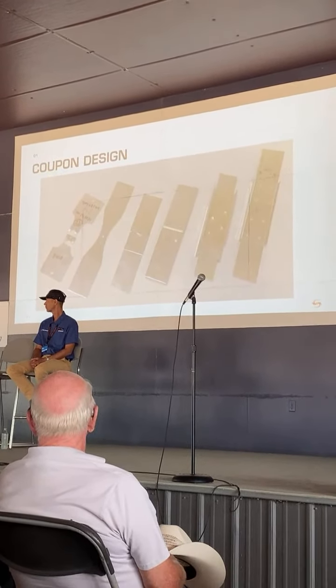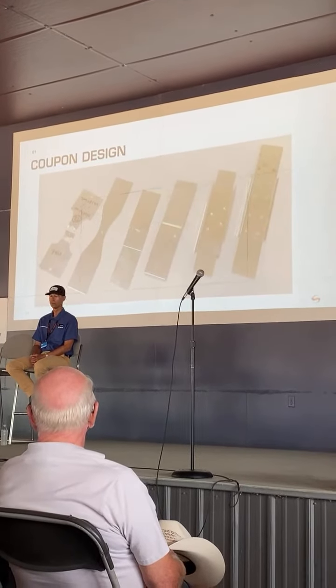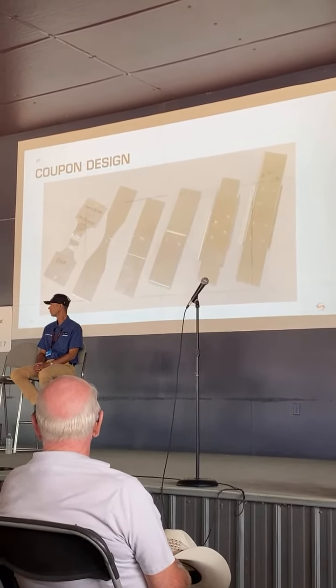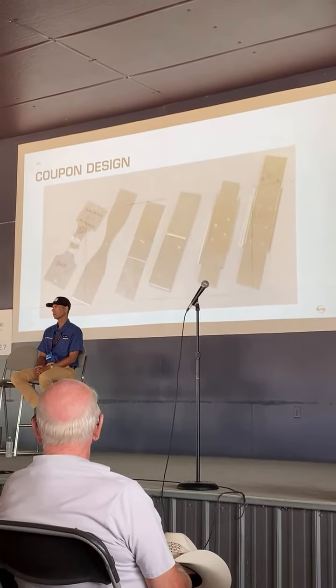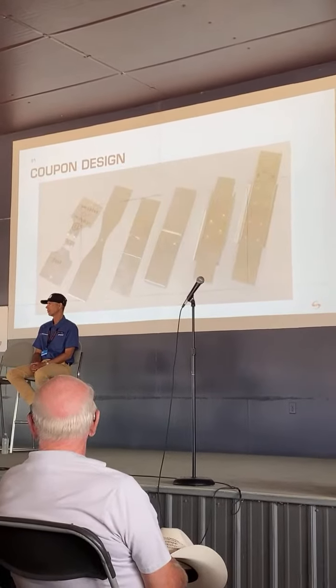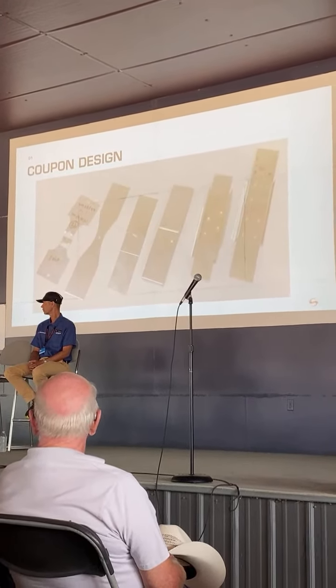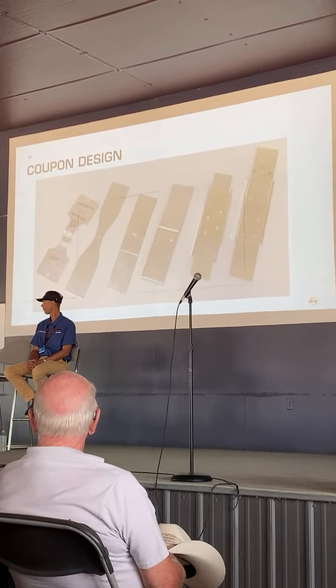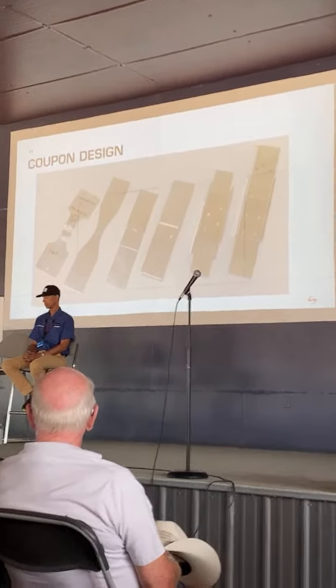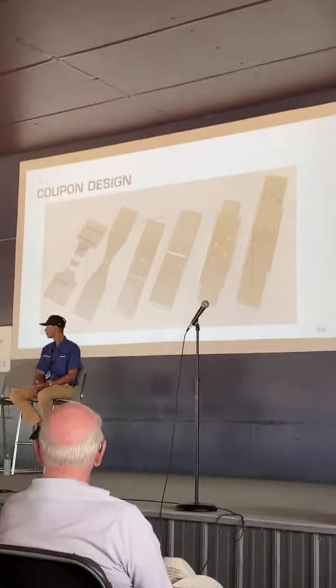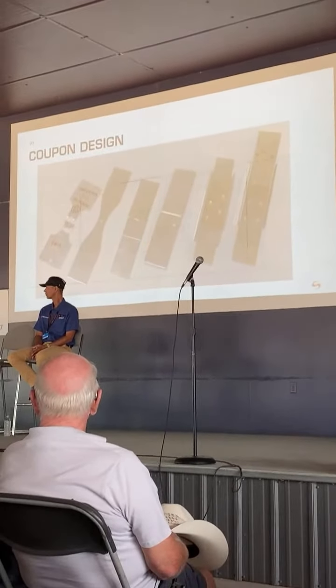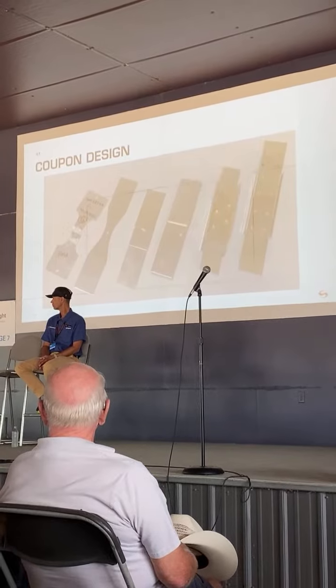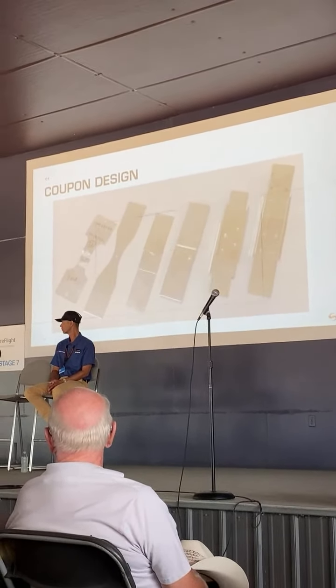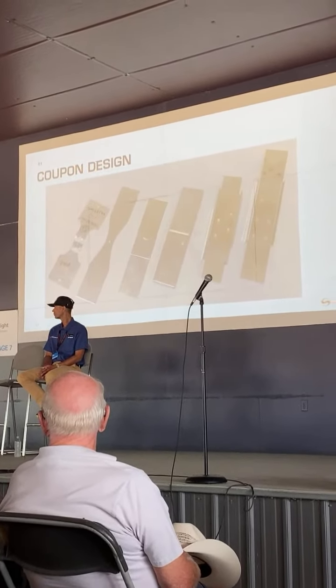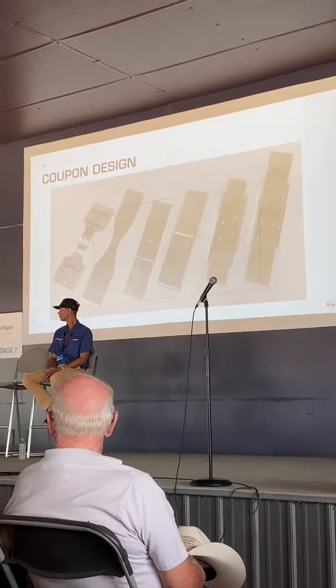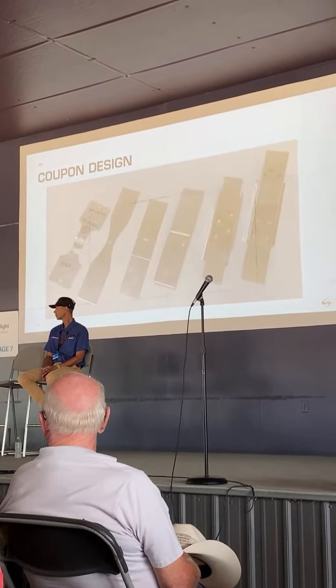Those coupons there were for final sized holes. The next coupon over is what we call a dog bone coupon, and that is not to test load through a rivet, but rather to test the edges of the parts. We want to be sure that the edges of the parts would not be affected by the laser cutting process. The one next to it has blind rivets in it, and we just want to make it clear that in the initial testing and subsequent testing, we have tested all different fastener types that you would see in laser cut holes. That coupon there laps the material over top of one another. So it's a single lap, and that's somewhat indicative of what happens in the airplane, and I'll show a graphic of that later.